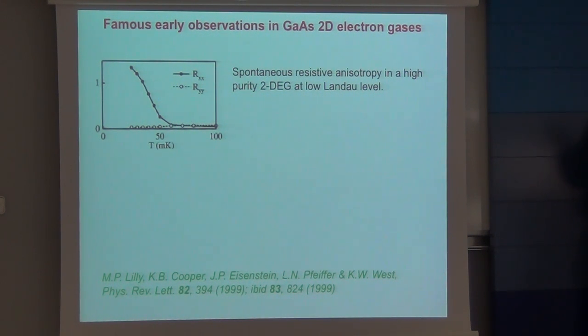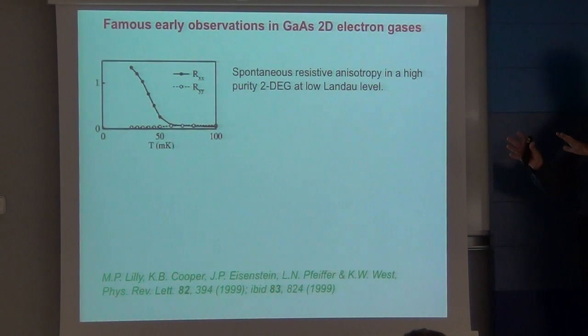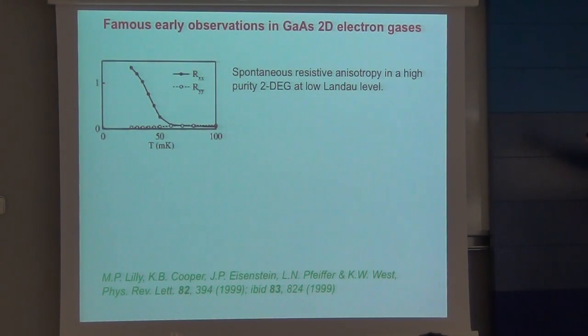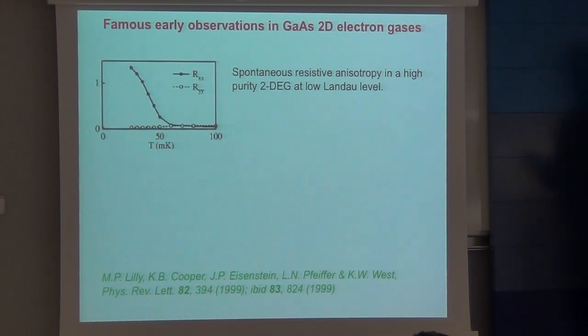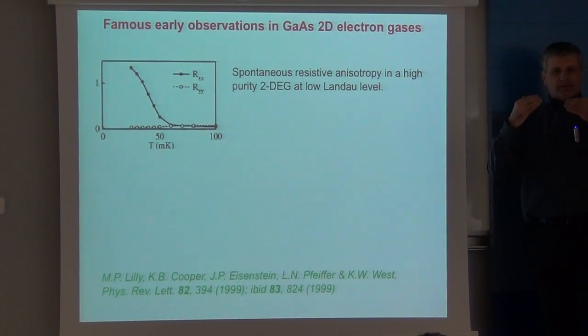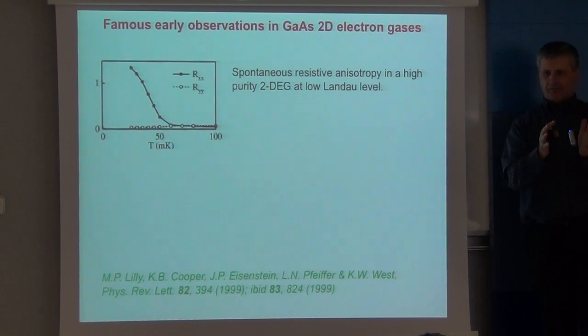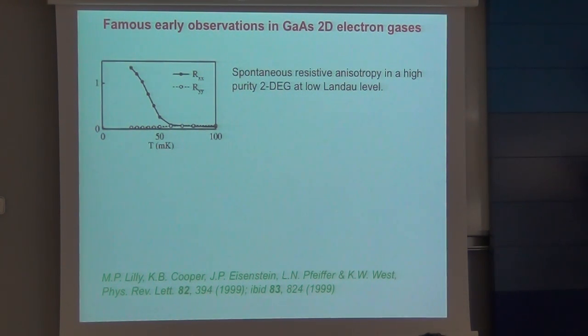And so he started to look at not the lowest Landau level where the fractional quantum Hall effect took place, but he started to look carefully at the properties of Landau levels between there and where he had the Fermi liquid. And what he discovered in those Landau levels, there's two Landau levels below the fractional quantum Hall state, in which he discovered that a system which seemed to be isotropic in the x and y directions in all the other Landau levels went very anisotropic for these 2 Landau levels. And that carried a lot of credibility because somehow he was doing a tuning from a definitely isotropic to a definitely anisotropic state, and it was extremely difficult to see in a device how that could possibly be coming from any structural effect. That had to be an effect of the electron-electron interactions in some way.